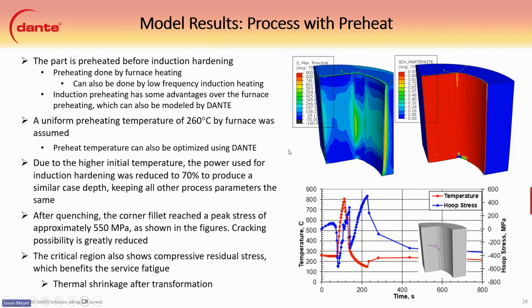The uniform preheating temperature of 260 degrees was used, and this is just assumed. We can also look at different temperatures, and optimize them, but for this one we used the 260 degrees. So due to the higher initial temperature, the power used for the inductor was reduced to about 70% to produce the similar case depth. And this keeps all other process parameters like the quench and scanning speed and everything the same.